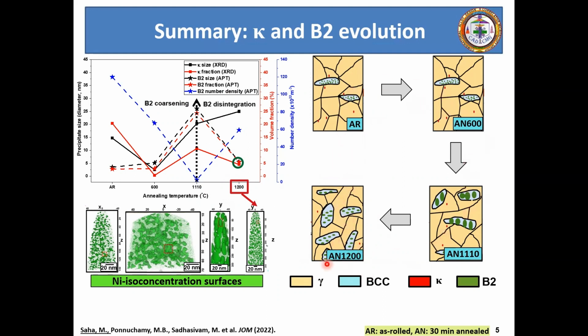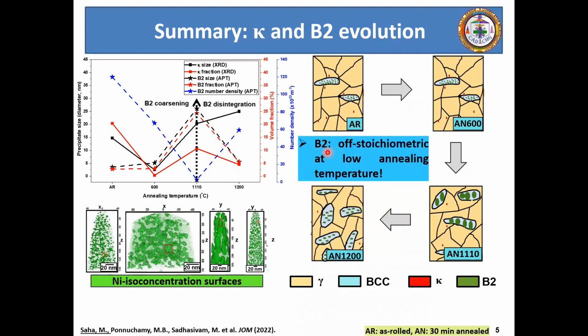So now, having known this, when we investigate the composition of the B2 phase in all these four different conditions, what we can clearly observe is that the B2 phase remains non-stoichiometric at the low annealing temperatures, that is, particularly in the as-rolled, 600 degrees and 1110 degrees annealed conditions, whereas a typical 1:1 stoichiometry is attained in the 1200 degrees annealed condition. Now the question is, in that case, how do we ascertain the presence of the B2 phase in the microstructure? So to do that, we have